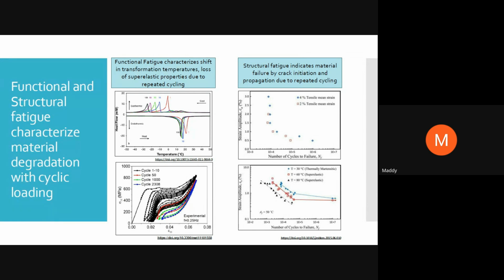So on the other hand, when you cycle it on the reverse transformation, the temperature starts increasing. Many researchers have explored this, and the reason they attribute to this degradation is that as you cycle, you generate dislocations, and your microstructure changes and starts creating more hindrance for the phase transformation to occur smoothly. And that is why you're seeing this shift in the transformation temperatures.